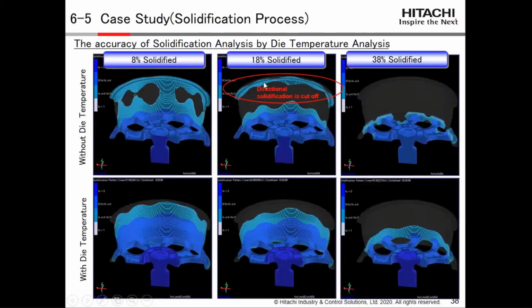By showing the image, it is separated into this area and this area. And when the area is solidifying, the shrinking area still remained. On the contrary, in this case, the shrink area is shifting from the product to the gate area. So the shrink area is moving from the top to the gate, and in this case, no shrink area remained in the product area.